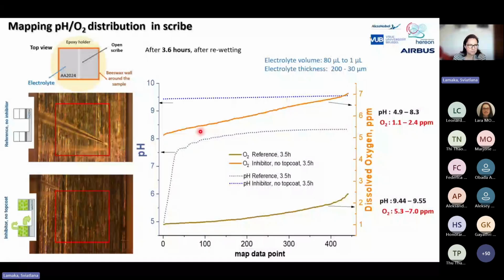And so we looked at why this might be happening, and with the help of electrochemical impedance spectroscopy, and also with SEM and thermodynamic calculations using Hydra Medusa, we proposed that magnesium forms soluble complexes with pyridine dicarboxylate, and this leads to destabilization of the PEO layer composed of magnesium phosphate and oxide. And this really then disrupts not only the porous layer, but also the barrier layer on PEO.